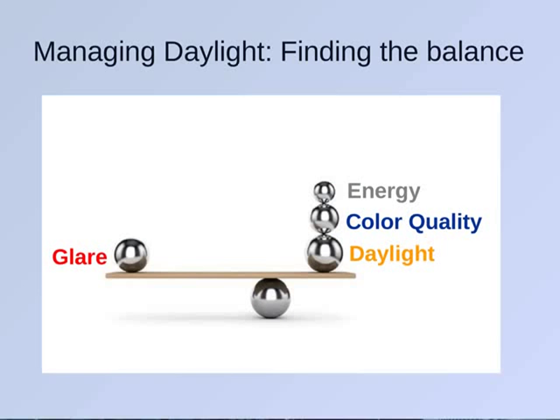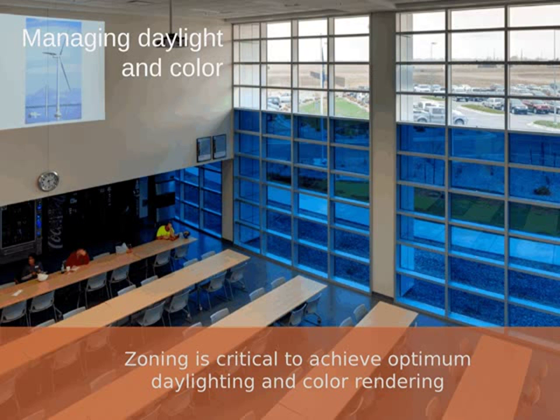Now we're going to talk about the zoning, which is important in order to strike the right balance, and that's what you're seeing here. So that ball bearing that represents the fulcrum, that's really striking the right balance between glare control on the left and then energy, interior color rendering, and then daylight on the right. So I'll illustrate that through the next series of slides here. Starting off, well, this is an example here of a two-story atrium. And by leaving 10 to 15% of that glazing facade in the clear state, you're bringing enough daylight into the interior spaces so that it doesn't have that overly bluish aquarium sense to it.